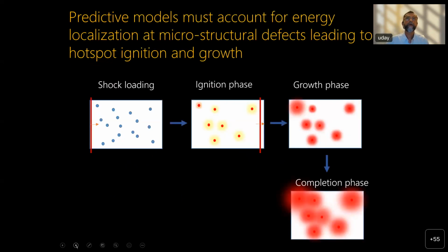in this talk. So fundamentally, the mechanism that leads to sensitivity at the mesoscale is when you load a shock, you form hotspots, and these hotspots typically localize at defects in the material. So these could be cracks or pores or something. There are many mechanisms of hotspot formation from these defects, but in the shock regime or high shock regime, when we're talking about 10 GPa plus or even let's say 6 GPa plus shock loading, the primary cause of localization is the collapse of pores. So these pores collapse.